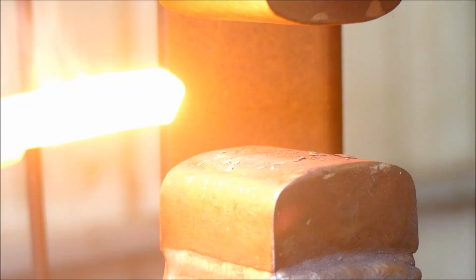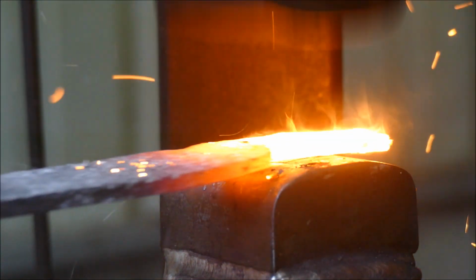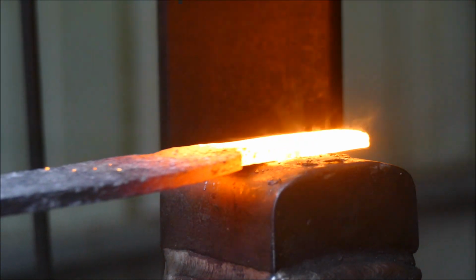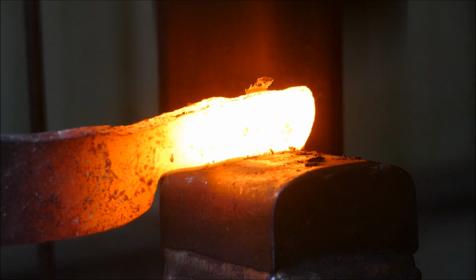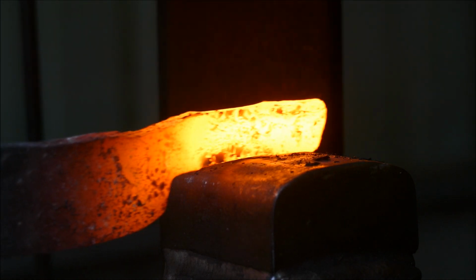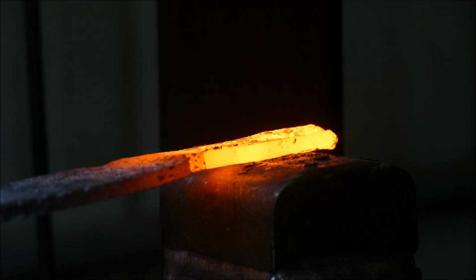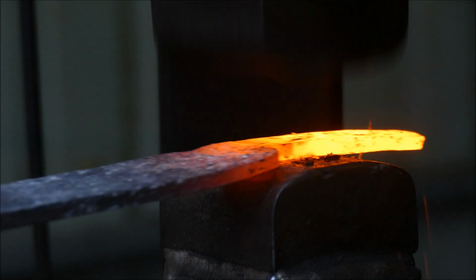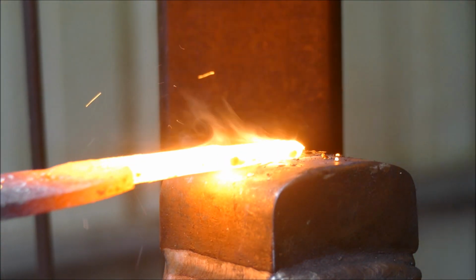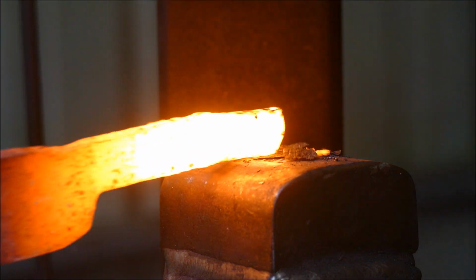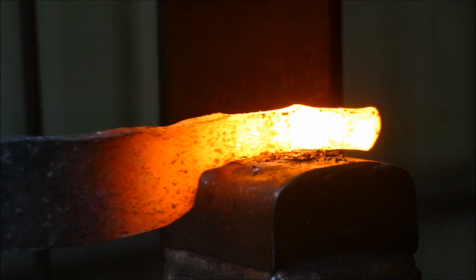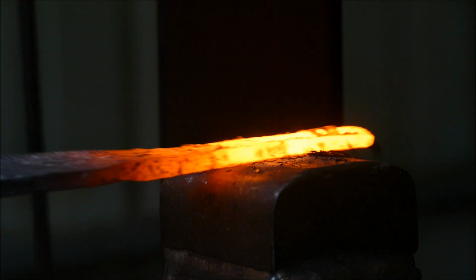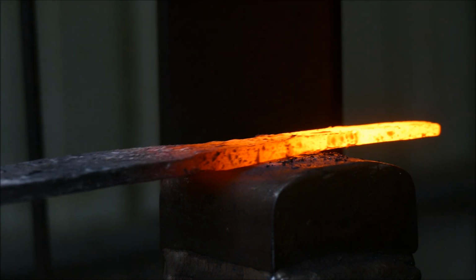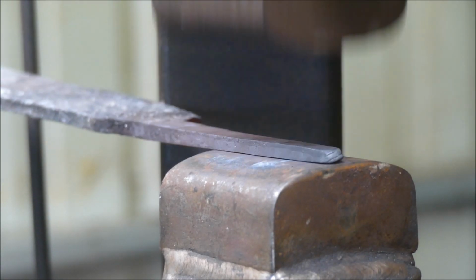So traditionally they didn't have fluxes available, or if they did they would have used something like silica sand. So another idea is that if you actually entomb the high carbon steel in a low carbon or pure iron, you'll actually protect it from the oxygen in the air when it gets to critical temperature. I actually achieved this by forge welding a piece of high carbon into a wrought iron axe, and it came together beautifully without the need of flux at all.